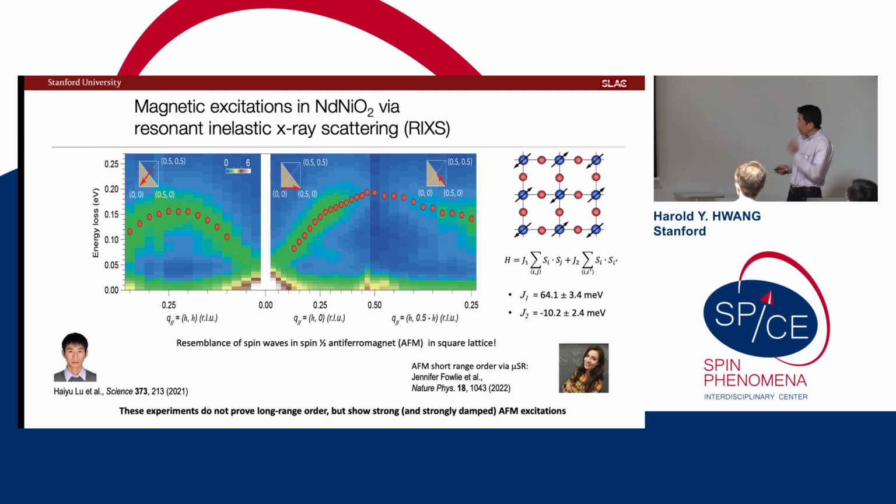Now, of course, the other key difference here is that the excitations we see are strongly damped. And so we find a linewidth that is larger than the experimental resolution. And to leading order, it looks very much like the spectra you would find in a doped cuprate. So our qualitative understanding is these electron pockets that I alluded to, the fact that we have this unusual electronic structure, is probably giving us damping channels even for the nominally undoped end member. So that's one message here, that we have strong magnetic fluctuations that seem to be prevalent in this system.